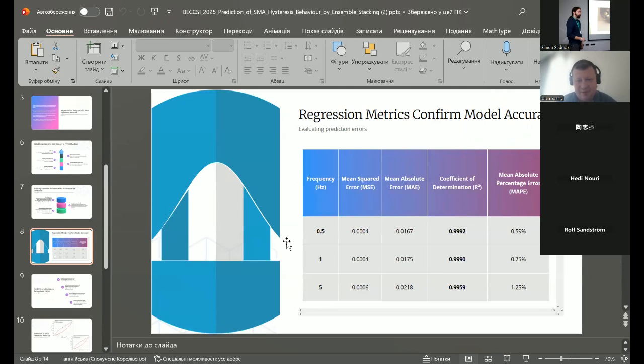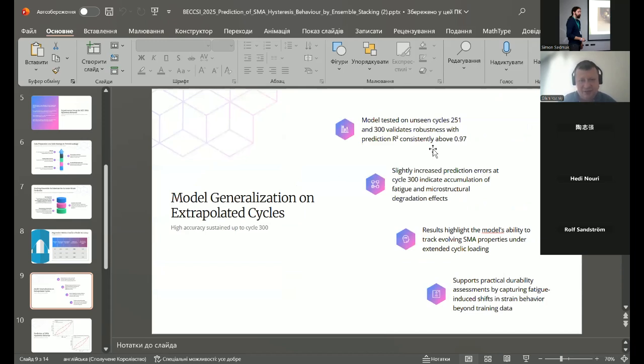The prediction errors were as follows. You can see on the graph the three test frequencies 0.5, 1, and 5. As you can see, the coefficient of determination is quite high in each case, and absolute error is less than 1.25% in all cases. Model generalization on extrapolated cycles: high accuracy sustained up to cycle 300.